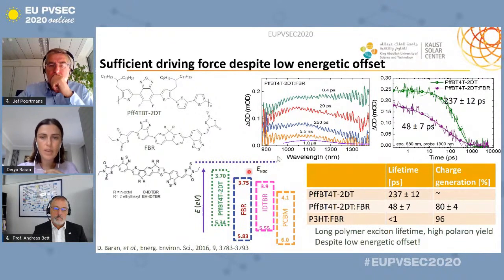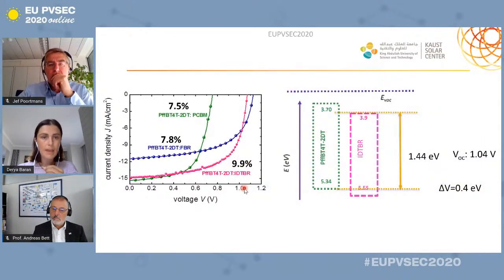So in this case, what we have seen was also quite a nice long polymer exciton lifetime, because it was a semi-crystalline donor, and then high polaron yield. This was very interesting and exciting, despite this low energetic offset from this particular blend. And when we look at the solar cell performances, we were able to achieve 10% solar cells with really nice open circuit voltages, about 1.04, which was also another set limit at the time, going beyond 1 volt with decent external quantum efficiencies.